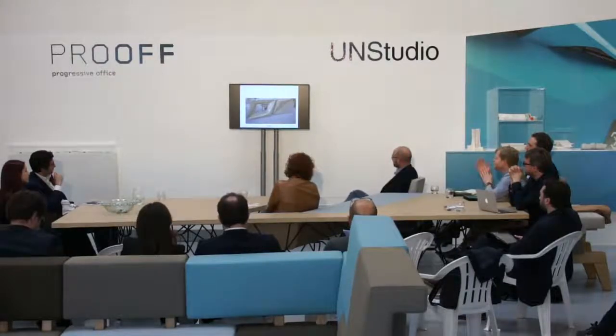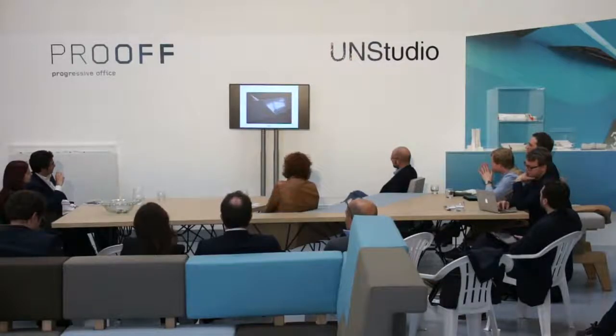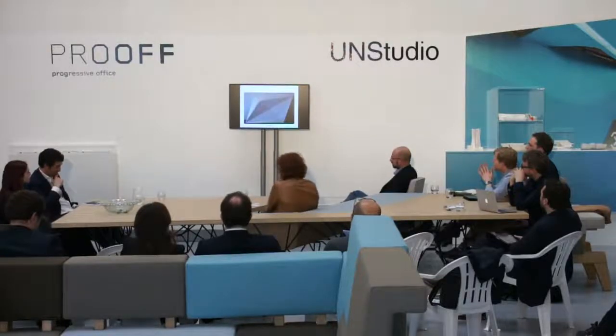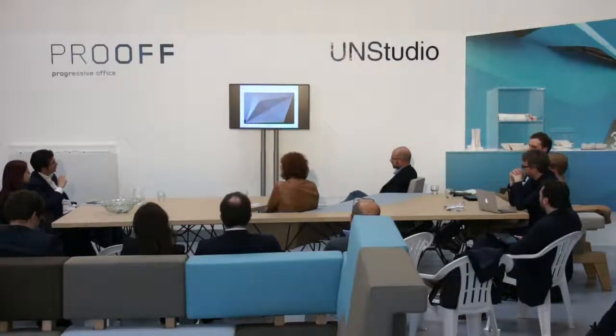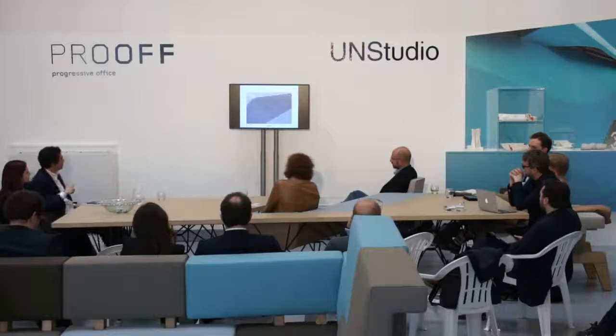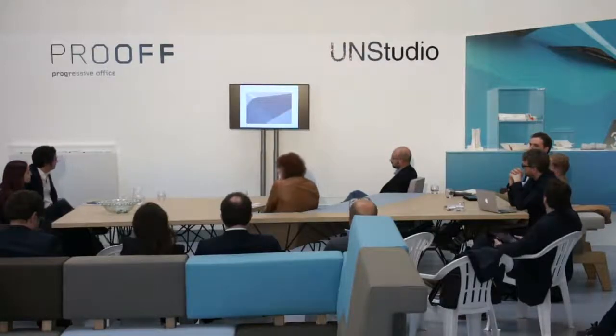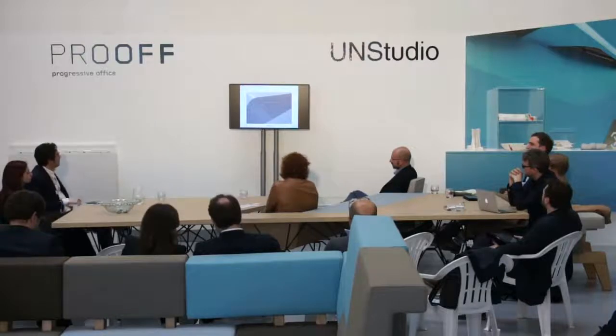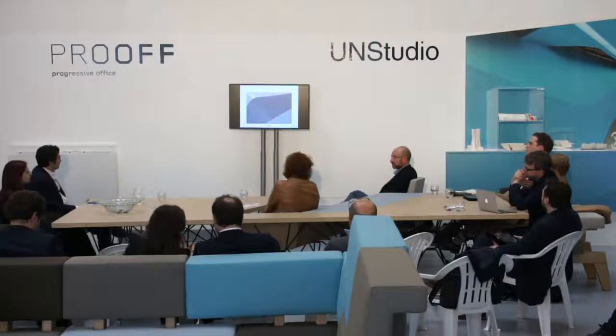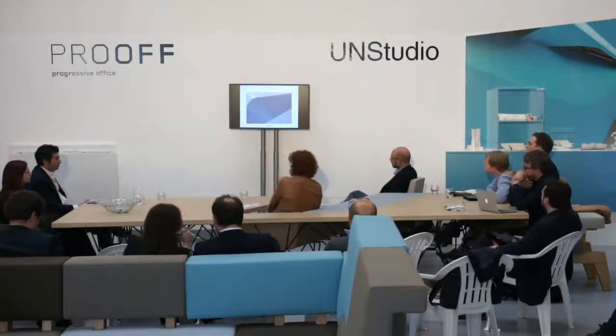You can see the part coming out of the mold is already very accurate and defined. You see the complex shape there. And this was after the finish application. It was a mix between textured and smooth finish, which was actually quite attractive, as seen here. This is also an advantage with FRP, that you can create very different appearances on the surface, which I think is very difficult with aluminium, for example, or concrete itself.